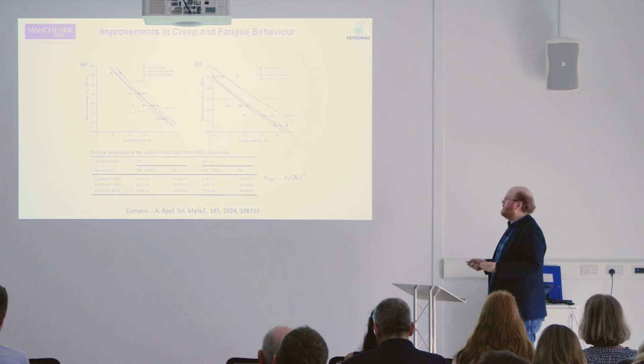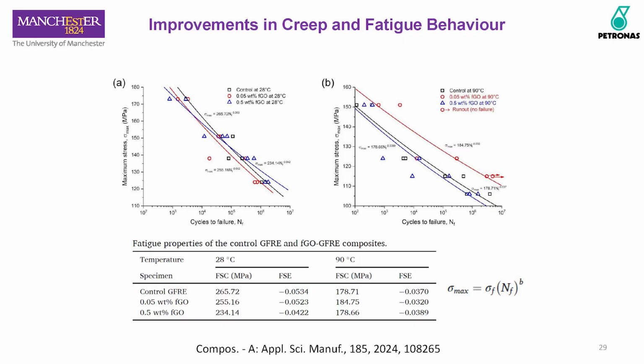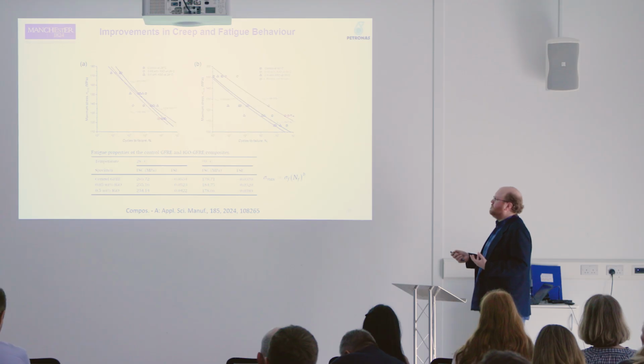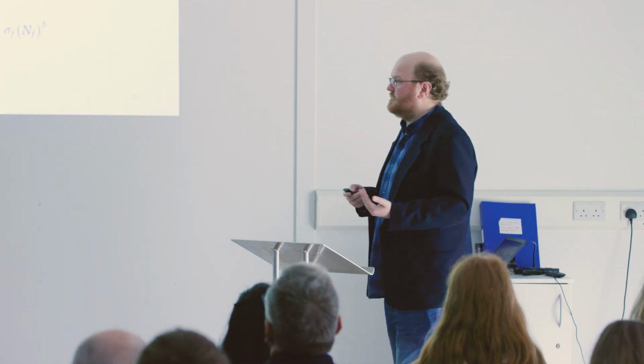And it's the same for cyclic load. If we look at fatigue, where you're constantly loading and unloading a material, particularly also at higher temperatures, the control one here, we can see this is an S-N curve. This is basically the stress before failure versus the number of cycles to failure. And so you get a curve like this. The red one shows it with 0.05% of that functionalized graphene oxide at 90 degrees. And some of these are lasting millions of cycles before they're failing. And because this is a logarithmic axis, that's actually a significant improvement in the fatigue behavior of these composites. So it's not just the modulus goes up or the strength goes up in a single measurement. These actually, in real world conditions, give us much better benefits than we may be expecting.